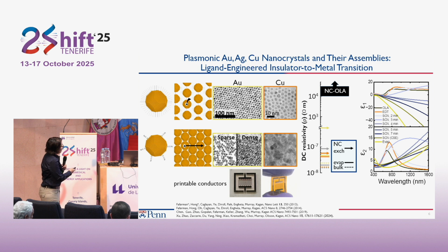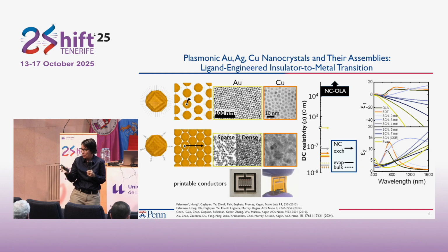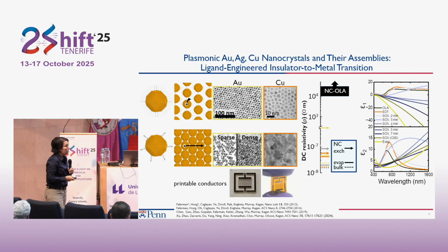And so, as I said, this is really an opportunity for surface chemistry. One thing that's possible in nanocrystals is that we can really go in and address what's at the surface. We can take one ligand and swap it for something else. In this example, one of the ones that we like is these short, compact inorganic salts. In the first example, we use ammonium thiocyanate, ammonium chloride, lots of different salts. If we do that, we can swap the ligands that are on the surface for something new.